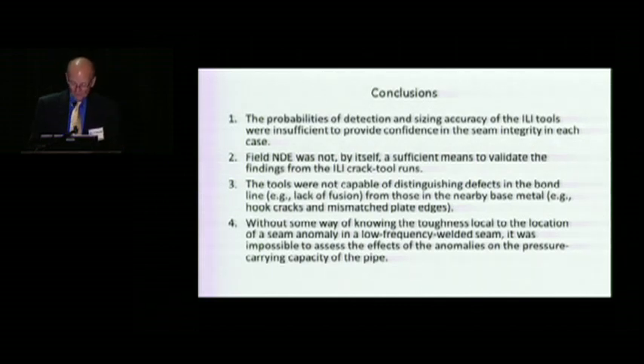Because, and by the way, this was pointed out by Brian this morning, if you don't know the toughness of the material you're dealing with, then all the good data you may have on sizing and all your models aren't going to do you any good, because the toughness becomes a critical element. And we certainly determined that to be the case in this study. We did this study for 13 tool runs, and that's what we came out with.